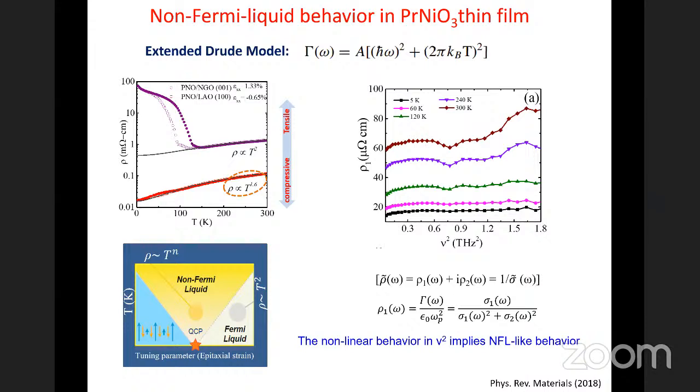So this was another thing that we could prove till now, that the charge density wave is the ground state of the rare earth nickelates, and there's a definite effect of the disorder on all kinds of low energy phases. We also showed that when the system is driven from an insulator metal transition by the application of epitaxial strain to a completely metallic state, there's a transition from Fermi liquid behavior to non-Fermi liquid behavior. Of course, we didn't show it; we just followed a study.